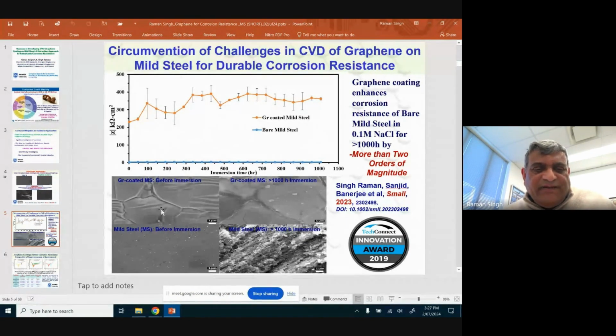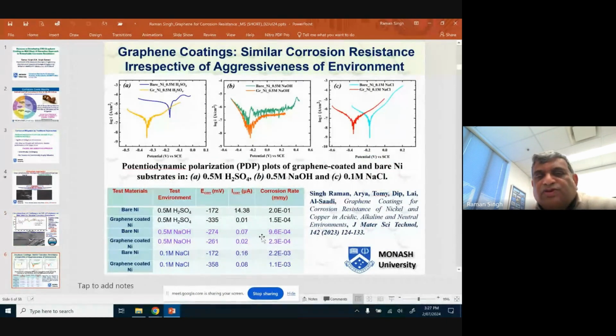So seeing is believing. As you can see, that is graphene coated mild steel exposed to, again, seawater for over 1,000 hours, no corrosion at all. Whereas simple mild steel, a 2 millimeter thick sample, will be finished in a few hundred hours. So that's what I'm going to show you.